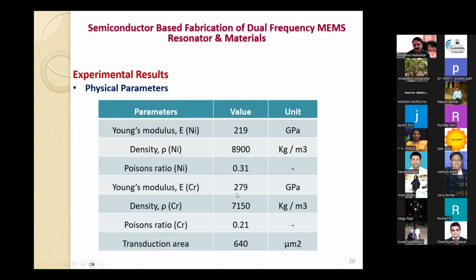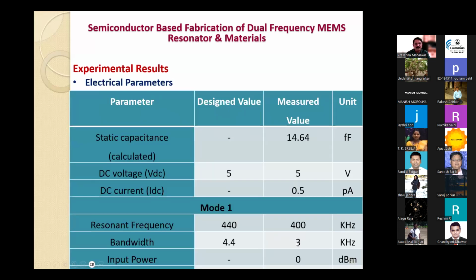The Young's modulus, density, Poisson's ratio, etc. we have measured here. And finally, the transduction area, that is the area which is overlapped between the beams and the input and output electrodes, was measured to be 640 micrometer square. After these mechanical and physical parameters, the electrical parameters were the static capacitance and the applied DC voltage. The current that we measured was only 0.5 picoampere. The resonant frequency changed because of the change in the physical parameters: the length was 76 micrometer, but the width of the coupling beam and the width of the CC beam after fabrication changed to 8 micrometer.